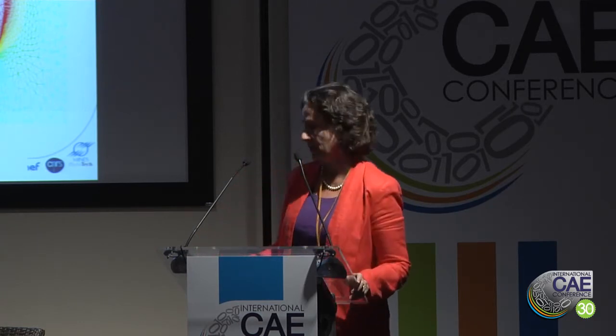There are sometimes voids. The voids increase or decrease. It's very important to be able to simulate this. So how does the void operate? There is the nucleation, the very beginning. So you imagine that we have here a void, a matrix, and here is just a criterion based on the normal stress. And when we reach this threshold, we have the nucleation of a new germ here. So we can see this new void appearing here. This is one of the methods.